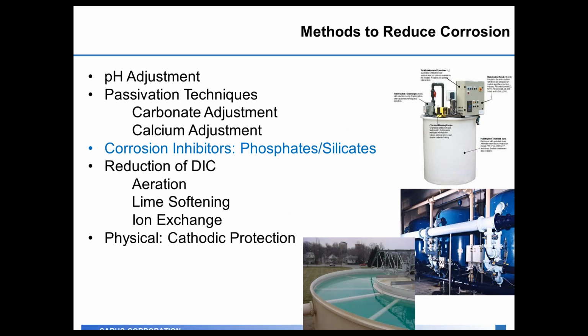When we talk about methods to reduce corrosion, there are some standard techniques that most water plants will take into account. pH adjustment generally is the first one that most plants will consider because it's one of the easiest chemistries to add. Next would be passivation techniques, which would be adding carbonate or calcium adjustment to the water. So this would increase the amount of calcium carbonate in the water or the alkalinity in the water to help you have that buffering effect and help lay down a calcium carbonate scale. Finally, you can use corrosion inhibitors, which would be phosphates or silicates that can lay down a phosphate or silicate coating on the inside of the pipe.